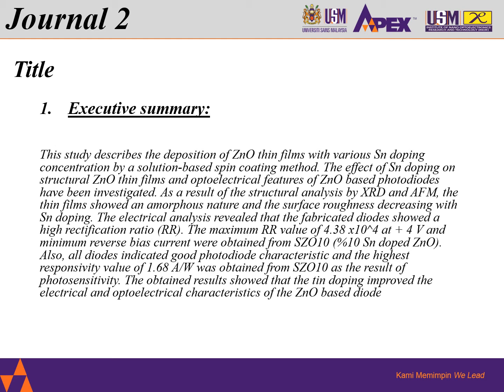the thin film shows an amorphous nature and the surface roughness decreases with tin doping. The electrical analysis revealed that the fabricated diodes showed a high rectification ratio, which is known as RR, the rectification ratio. The maximum rectification ratio value of 4.38 × 10^4 at +4 volt and minimum reverse bias current were obtained from SZO10, 10% tin doped zinc oxide.